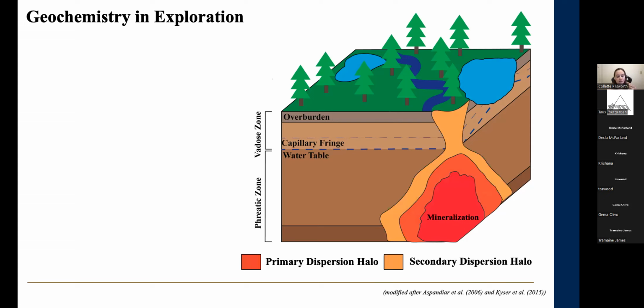And you also get secondary dispersion halos, which are associated with the remobilization of elements from the ore or primary alteration zone after ore deposit formation. And this tends to result in a secondary dispersion halo which is larger than the primary. And we care about this as the bigger the geochemical footprint of a system, the more chance we have of detecting that geochemical signature, which is indicating potentially mineralization nearby.